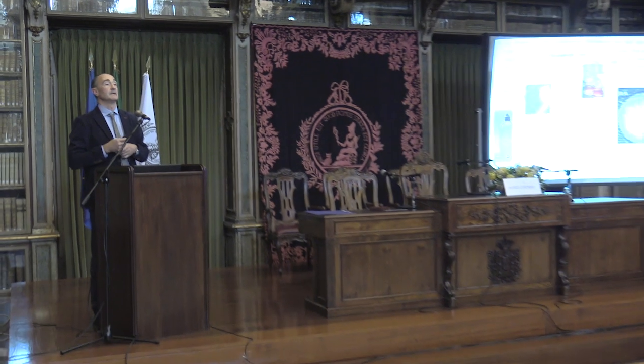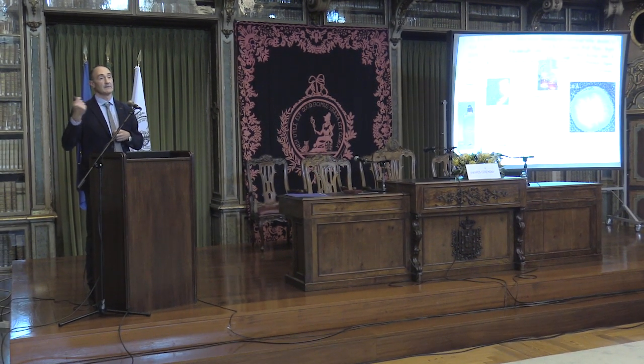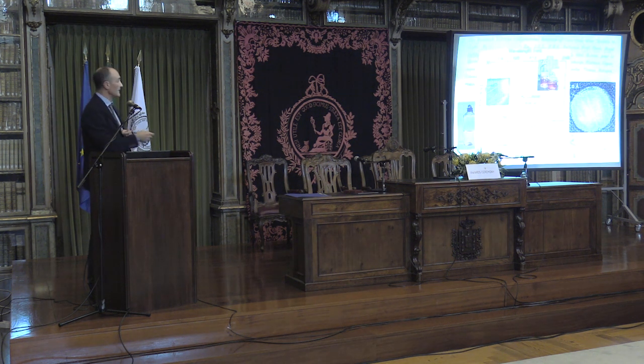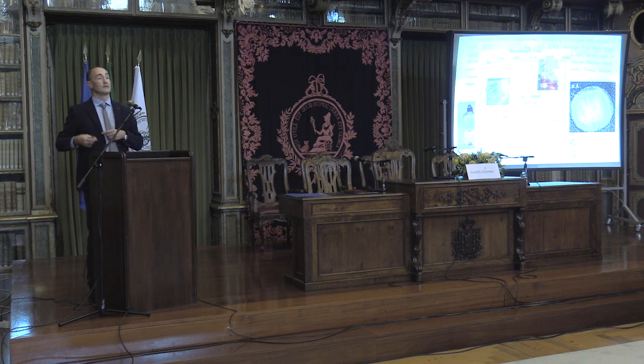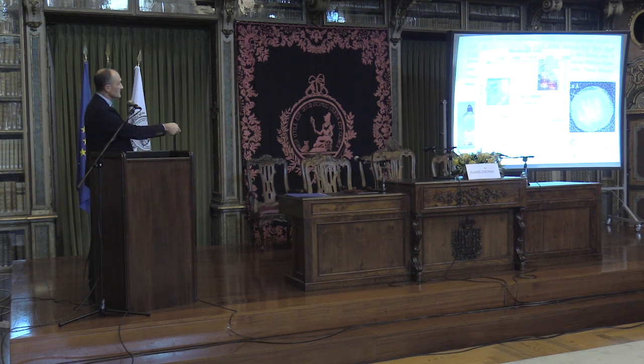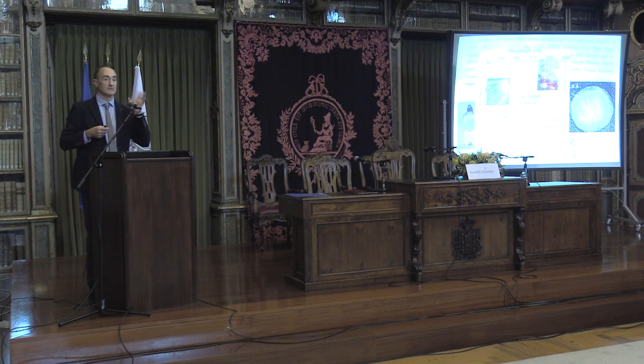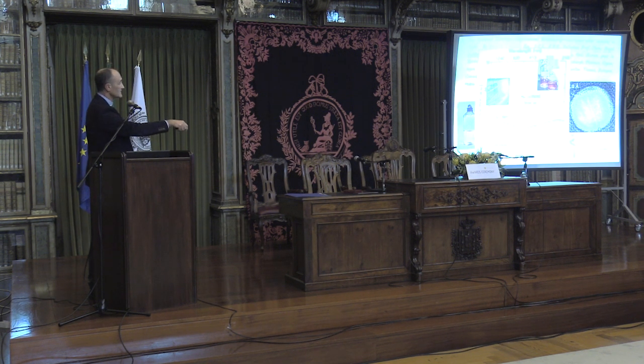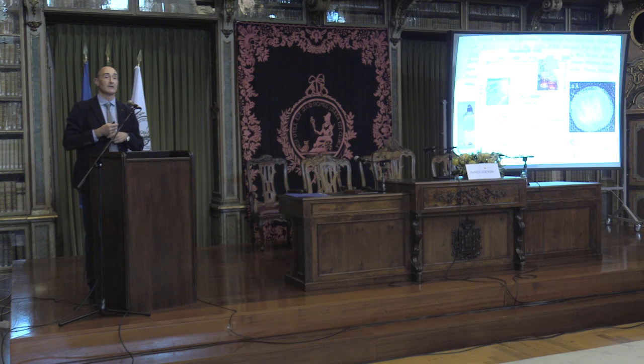But Faraday was also working with thin metallic films, and he was somehow beating small metallic leaves and making them thinner and thinner, trying to observe if at a certain point visible light can actually go through the film. And in this picture here, it's not very clear, but if you look close enough, you'll see that there is the typical golden reflection, but also in the shadow, you can see some bluish tone, which is related to this dip in the absorption band of the film, meaning that light around 500 nanometers can actually penetrate partially and go through the film.